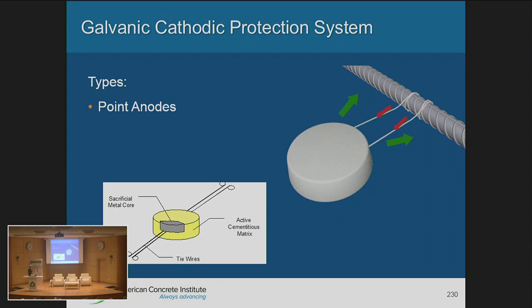There are different methods for adding this energy. We have the point anodes, where you have a small cylinder or disc with a sacrificial metal in it, usually zinc. You attach it to the bar, and it protects the bar. Usually those anodes have a certain lifespan, a few years, and their protection is limited to about 150 millimeters from the anode itself. So it provides limited protection.